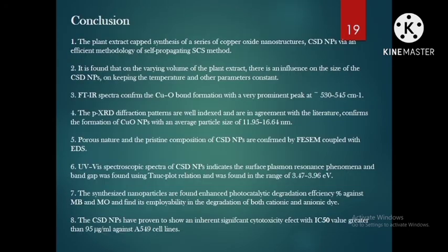The conclusion goes like this. Here we have developed an efficient, effective, rapid and cost-effective method for the synthesis of nanoparticles employing the solution combustion synthesis method. We have also shown about 90 to 93% dye degradation efficiencies of the nanoparticles against the carcinogenic dye. Also, we have checked the recyclability profile of the nanoparticles and the results show that even after the fifth cycle of experiment, the nanoparticles can be reused for further experiments.